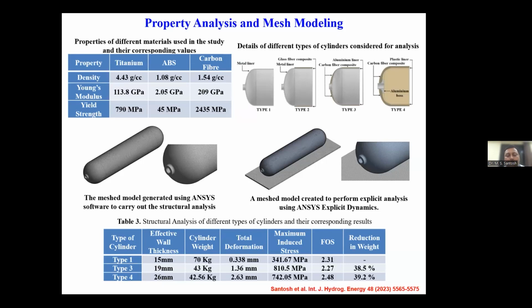So when you look at type 4, 2.48 is the factor of safety to which the cylinder has to be tested in order to ensure that the cylinder will actually abide by the norms of the industry and meet the requirements of a safe, secure, and strong cylinder which can hold such high pressures of 350 to 700 bar.